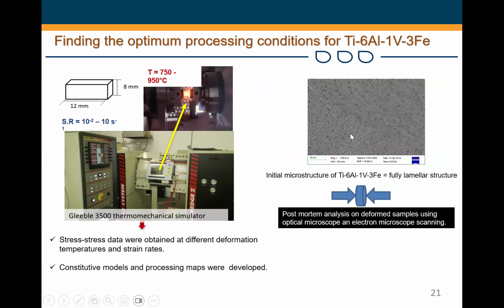And again, I'm showing you the typical microstructure of as-cast Ti6Al1V3Fe alloy. This is an alloy where 1 weight percent vanadium has been partially substituted with 3 weight percent iron. And we looked at a range of temperatures and different deformation speeds here. We wanted to see, would we have conditions that are detrimental to processing of these alloys? Then would we have conditions that will start giving us rounded microstructure? And the rounded microstructure, in technical terms, is called a globularized microstructure.